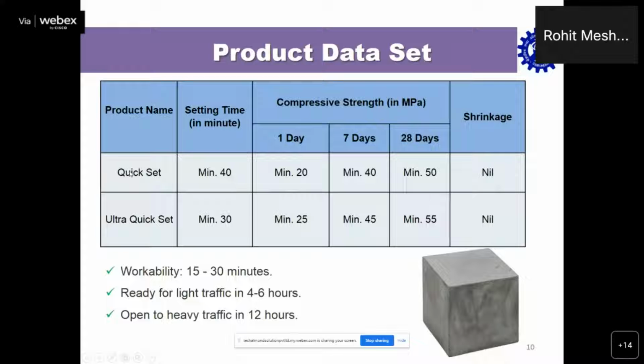So the two products we have developed, based on their setting times, one is at a minimum of 40 minutes, that is quick set, and another one sets within 30 minutes, that is ultra quick set. And the compressive strength after 28 days is as per the ASTM standard, and we have not found any shrinkage. The workability for this material is within 15 to 30 minutes. That is, it sets very fast.